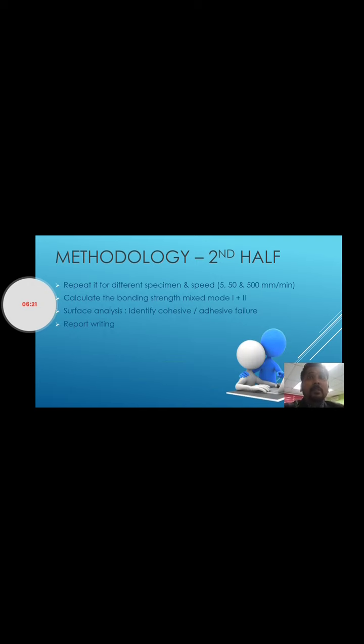And this is the second half. Repeat it for different specimens and speeds: 5, 50, 500 mm per minute. Calculate the bonding strength, mixed mode 1 plus 2. Then surface analysis, where you have to identify cohesive or adhesive failure, and the last is report writing.